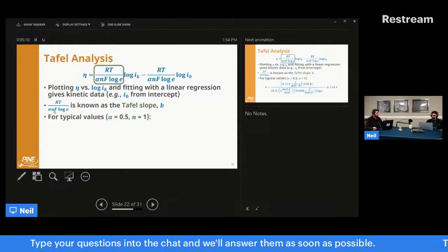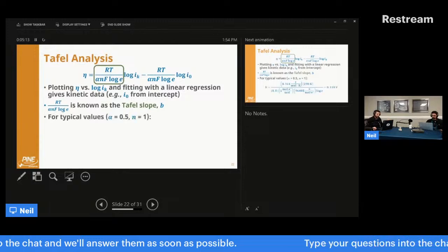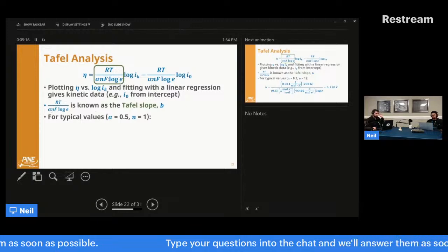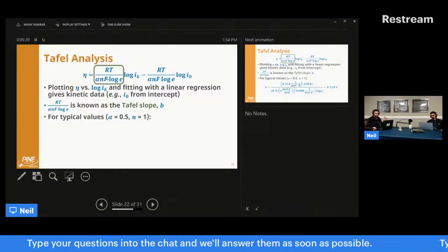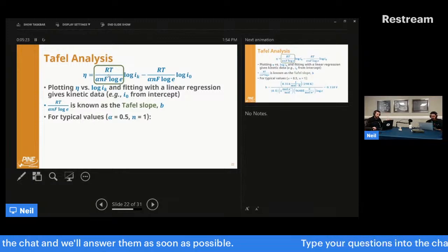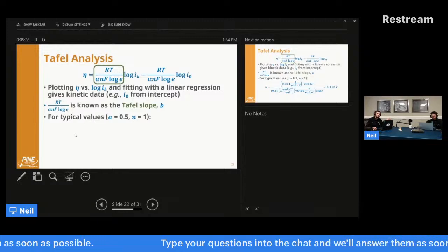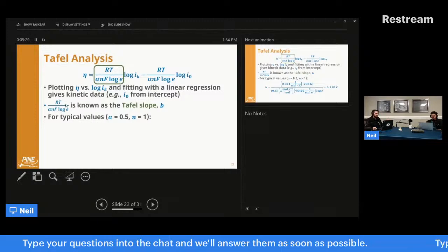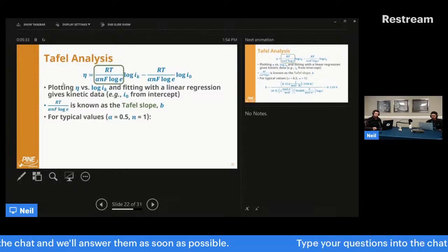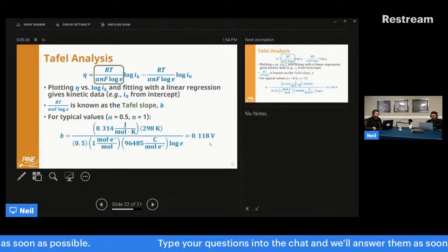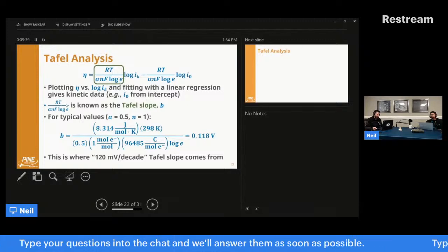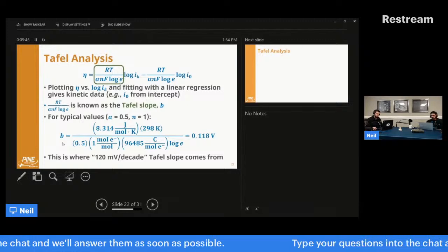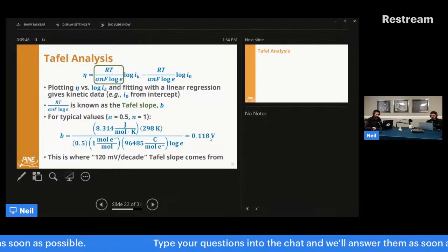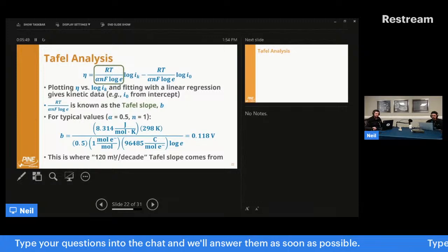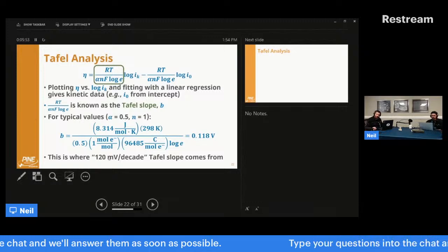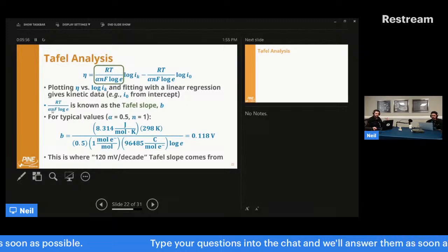Okay. So what it's telling us is effectively just kinetic information. It's giving us information about, is alpha 0.5? Is n 1? What was my temperature? But the most common thing people are getting is n, the number of electrons transferred. For things like the oxygen reduction reaction, people are looking for n to be 4. Basically you're looking for a deviation in this number, because if you plug in the most typical numbers like alpha 0.5 and n equals 1, the Tafel slope is 118 or 120 millivolts per decade. So deviation from 120 usually indicates that n is not 1.